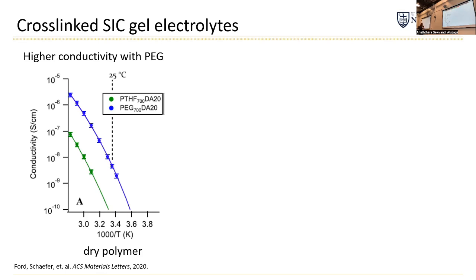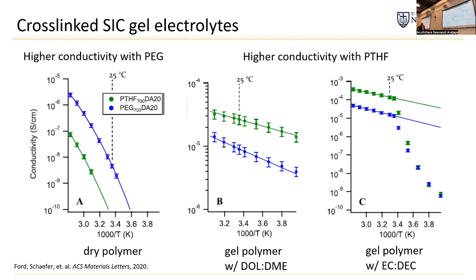But then he decided to swell these, and he swelled them in two different types of liquids. So in one case, he swelled it in a DOL/DME mixture. So this is an ether solvent mixture that's commonly used for lithium-sulfur batteries, but without any salt in it. He just put it in the solvent. And in another case, he swelled it with a carbonate-based mixture. And what you can see here is that in both cases, the ionomer with the poly-THF, with fewer oxygens in the polymer backbone, gives you higher ion conductivity.